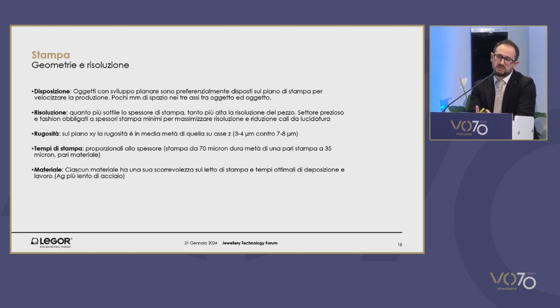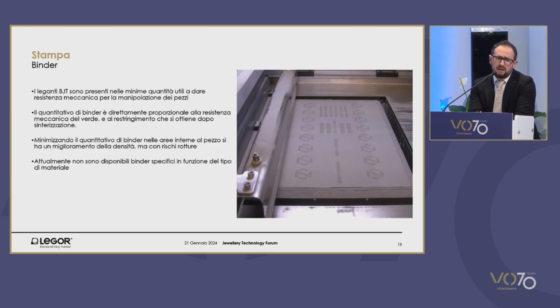With our powders, the roughness you obtain at the end of the printing process is approximately 4 microns on the XY planes. It is higher on the Z-axis, about twice as much. And this depends, of course, on the binder elimination phase.